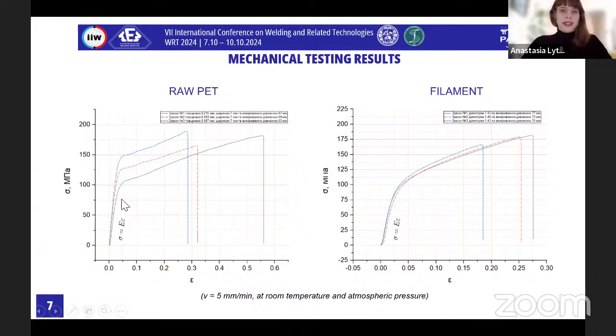If we analyze the curves on these graphs, the part of the curve that can be described by a linear equation needs to be isolated, and then we can use the following equation for finding Young's modulus for both raw plastic and filament. For this part that is described with a linear equation, and also the graph for filament on the right-hand side, we can see a structural difference from the one obtained for PET tape, because for raw PET, necking was observed along the entire length, and we can see on the graph how it forms the neck. But in the curves for the filament, there are smoother transitions from elastic to plastic deformation, and there are no very visible peaks indicating neck formation.